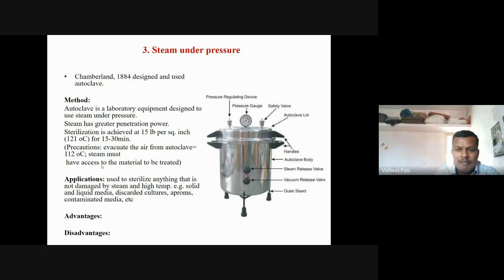And once there is continuous flow of steam, then you have to keep the pressure regulating device, or the vessel that we use in our regular pressure cooker. Because if air is present in the autoclave, then it can attain a temperature of only 112 degrees Celsius, as in a pressure cooker. It will not go to 121 degrees Celsius. So you have to evacuate the air from the autoclave. Then the second precaution: the steam must have access to the material that is to be treated. So these are the two precautions to be taken while we operate the autoclave for sterilization purpose.